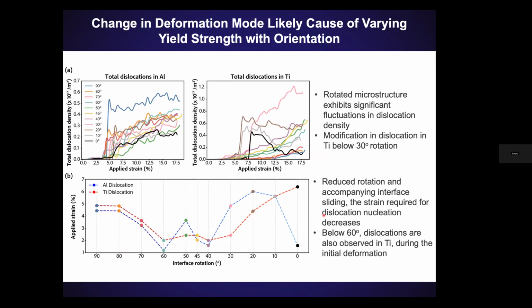In fact, we quantified the amount of dislocations, and I won't go into it, but as I've already told you, as you change that rotation, the deformation mechanisms in aluminum and titanium change. Essentially, there is a sweet spot where you want your interface to be, below which your material is going to be too soft. If we look here, these are dislocations. You don't want too many, you don't want too few. So I think the 60-degree orientation ended up being the highest yield strength for the interface.